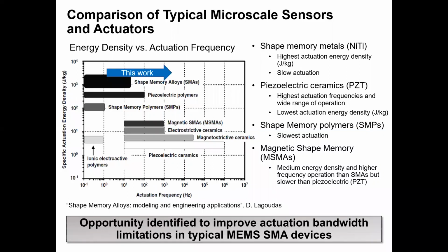So one of the main focus areas of this dissertation then was on the development of nanoscale thickness SMA films to improve these device bandwidth limitations. In the culmination of this work, I was able to achieve up to 3 kilohertz of reversible actuation speeds, which is an order of magnitude improvement over conventional SMA. And this was enabled through the miniaturization of the SMA films.